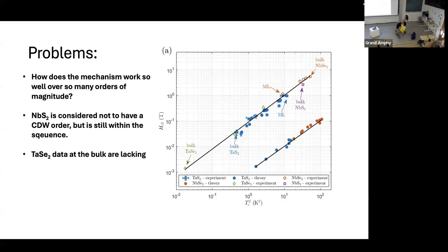So we opted for the one thing that can gap away your superconductivity: your Fermi surface. For superconductivity you need a Fermi surface, and if you start gapping away this Fermi surface in various regions in k-space, you have less and less population which can undergo pairing. So we opted for this particular theory.